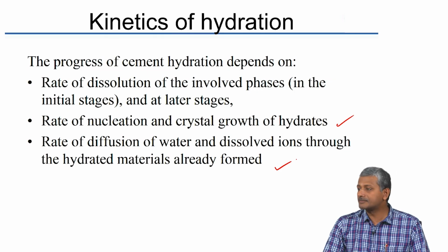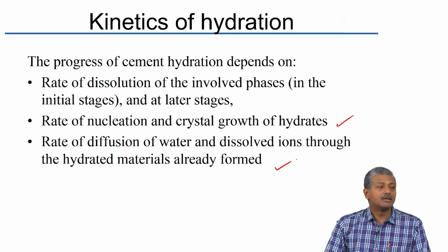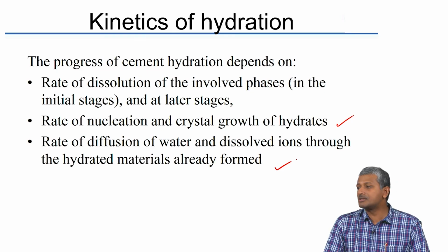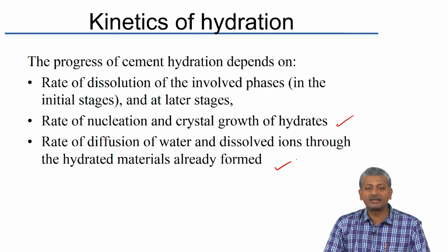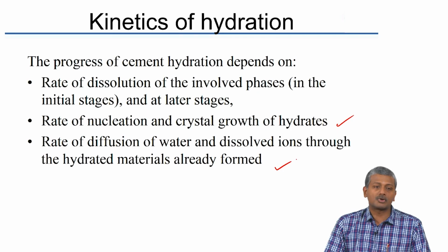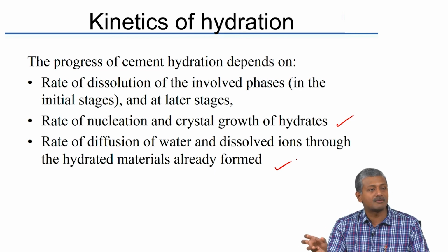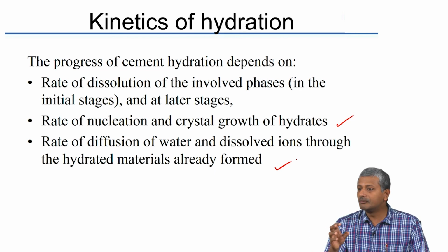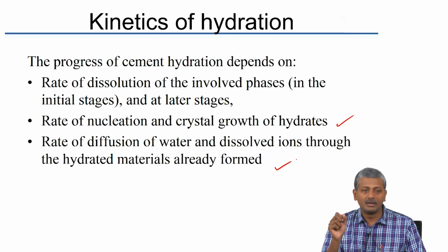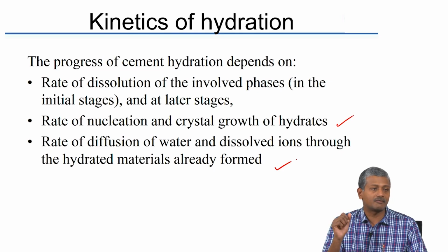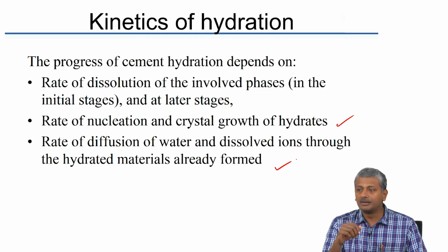What else? Yes, the impurities in water, because again please remember you have ionic concentration in the pore solution. If there are ionic species involved, they may affect one way or the other the dissolution process that is happening. The dissolution process can be affected by the ionic strength of the pore solution, and that may be contributed somewhat by the water also, which is why for the most part when we do construction we want water quality to be properly maintained. We need to check the content of alkalis and sulfates and so on in the water, and chlorides of course, in the water.